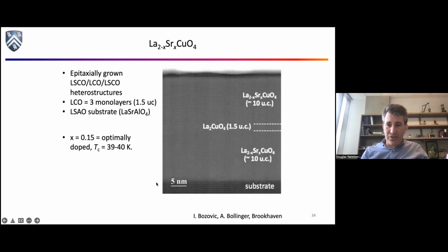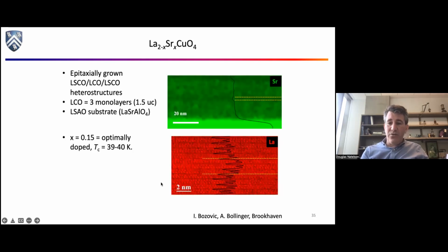electron microscopy image. And you need multi-million-dollar machines to take images like this, but they are very, very pretty. And this is the substrate, and this is open space up at the top. But this is the actual lattice, and you might think to yourself, well, okay, it looks pretty uniform. All you've done is Photoshop a couple of dotted lines on there. How do I know that there's actually this barrier in there? Well, it turns out with these very fancy microscopes, you can look at X-ray fluorescence. There's different ways to look at the elemental composition. And what you find is in that little thin layer, there's a little bit of excess lanthanum, a little bit of a deficit of strontium. That's how you know that's the barrier.